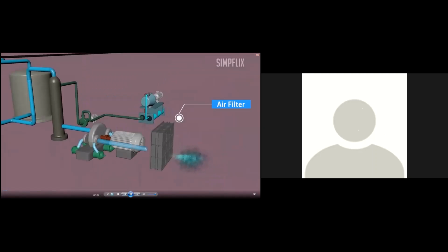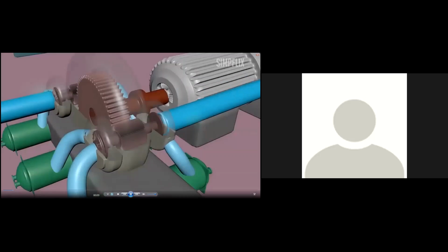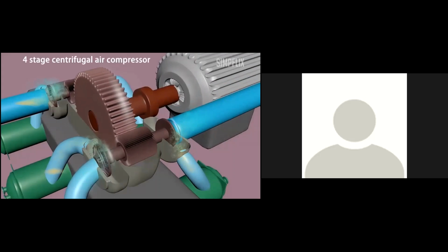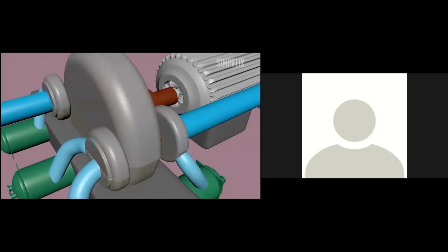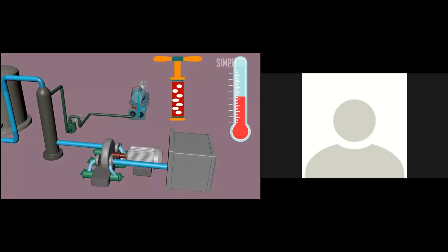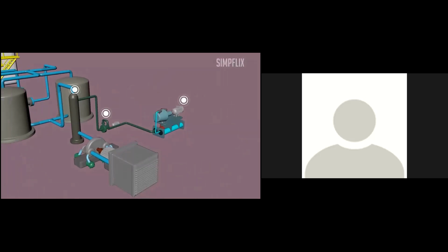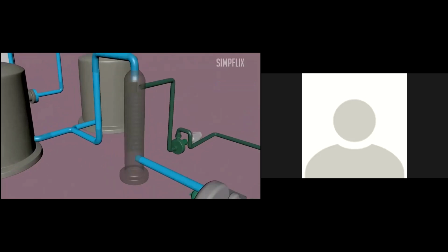Air from the atmosphere is filtered to remove dust particles and other hard impurities. Then the filtered air is compressed in a compressor up to 6-bar pressure, to make the air flow from start to end of the process. If the air is compressed, then temperature will increase due to increase in kinetic energy of air molecules. So, the high-pressure air at high temperature is cooled in the pre-cooling system to around 10 degrees Celsius using refrigerated water. During this cooling process, air will capture additional moisture, as it is in direct contact with water.